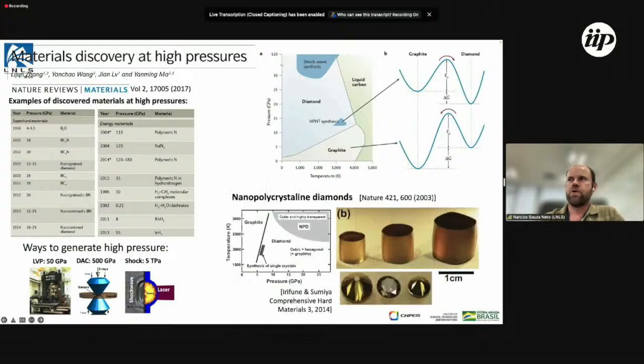But not only at phase transitions, actually we can synthesize materials at those conditions. Diamond is one good example. If we are in a well like that, at the minimum energy where the graphite phase sits, and we find a way to go to the other minimum of energy where diamond is trapped, we can make a transition from carbon to diamond. And that is experimentally possible. So we can synthesize diamonds artificially. This has been done for decades, but now all types of diamonds can be synthesized, like nanopolycrystalline diamonds, for example.